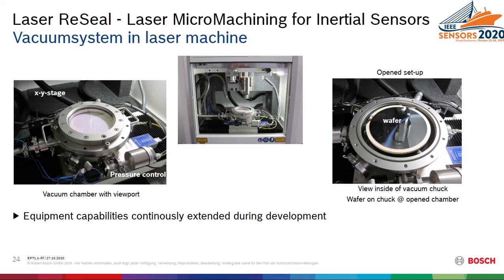In order to get a better statistic, we modified the stage and used a circular vacuum chamber where it was possible to clamp a whole wafer and also to control the pressure more precisely. Here you can see some pictures of the dedicated tool, including a wafer chuck and the viewport for the laser light. Main challenge during the time of development was to hit the vent hole in a precise manner. It turned out that it was rather important to seal the vent hole precisely in the middle, because otherwise a risk of crack formation, which took us a lot of effort, occurred.